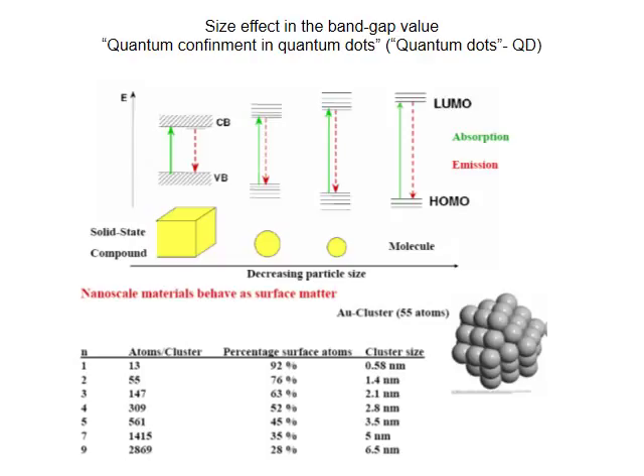In this case, we go from the solid, with its valence and conduction bands, to the molecule, with its HOMO, highest occupied molecular orbital, and LUMO, lowest unoccupied molecular orbital. Here again, we gather together the physics and chemistry languages. In this diagram, you can observe the increase in the band gap. CdS powders, for example, are orange in color for micron-sized grains. Decreasing the size of the crystals, one observes a yellow color for nanometer-sized crystals.